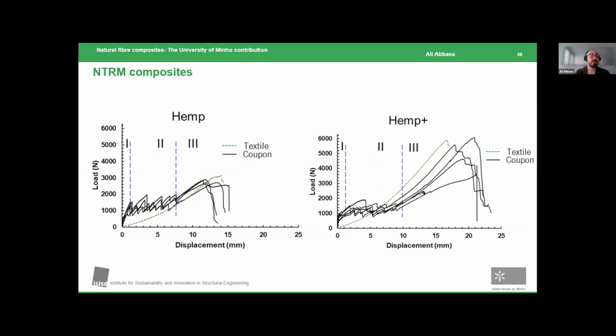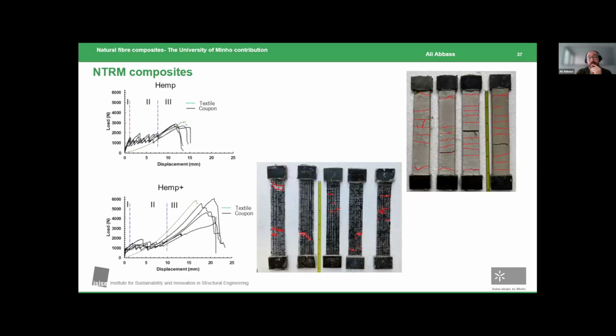Here you will see the results of the tensile test on coupons, and you could see very clearly these three distinctive phases appearing in both the volume fractions. And in all of them the transition is very clear from one phase to another, highlighting the good accommodation of tensile stresses from fibers to mortars and so on. So here you would see the cracking along the fibers, along the composites, and it is actually very interesting because it's in the same order of the effective bond length established within the pullout.